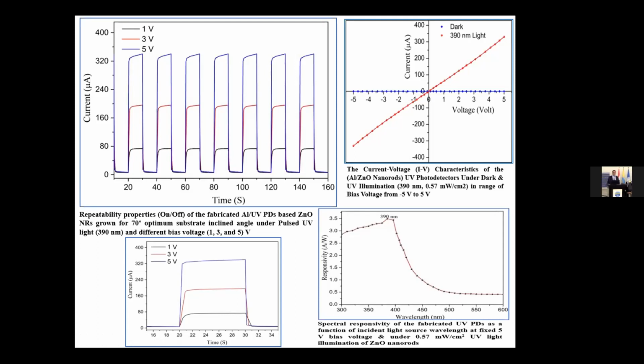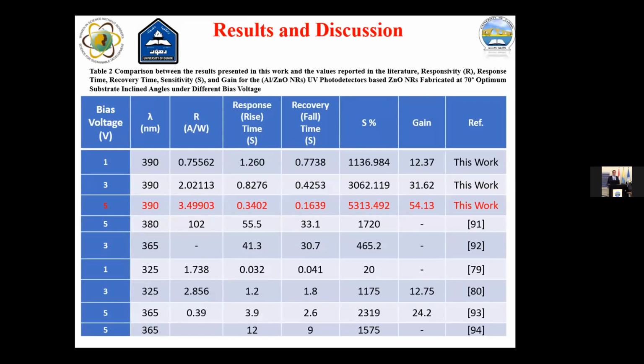The rise time is about 3 seconds, and the fall time is about 2 seconds. Also, this table shows the comparison between my result presented in this work and the results reported in the literature, such as responsivity, response time, recovery time, sensitivity, and gain the first one is 1 to 5 bias voltage. This is for my UV photodetector.